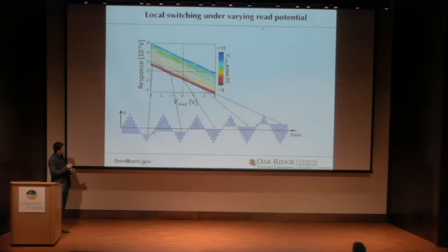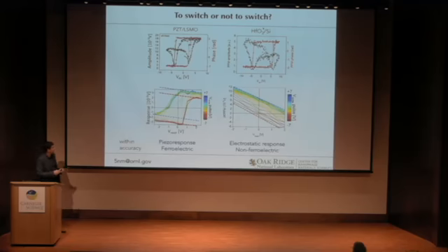This is an actual response of hafnium dioxide as a function of applied DC read bias. And what you see is just a sequence of straight lines. And remember that electrostatics is very strongly dependent on applied DC bias. So this signature alone immediately rules out ferroelectricity within the measured accuracy. And to put this point more emphatically, here's the comparison of this protocol on PZT and hafnium dioxide, and you can very clearly tell that even though these look very similar, these two behaviors are dramatically different.